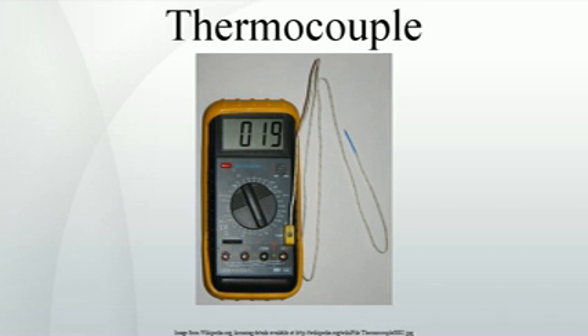Type B. Type B thermocouples, PtRh 70% per 30% and PtRh 94% per 6%, by weight, are suited for use at up to 1800 degC. Type B thermocouples produce the same output at 0 degC and 42 degC, limiting their use below about 50 degC. The EMF function has a minimum around 21 degC, meaning that cold junction compensation is easily performed since the compensation voltage is essentially a constant for a reference at typical room temperatures.